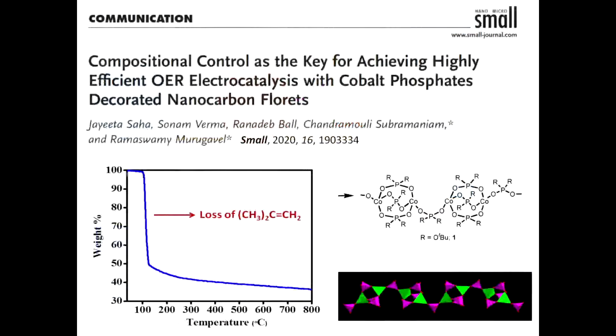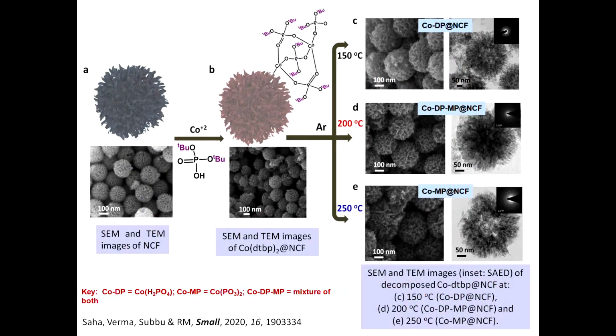If you had followed this TGA, at this point the dihydrogen phosphate is converting into metaphosphate. So what you have at 200 centigrade is a mixture of both dihydrogen phosphate and metaphosphate. And now you hit 250, by the time you have completely exhausted all the POH groups, and what you have is only the metaphosphate. So essentially, dihydrogen phosphate is one extreme, metaphosphate the other extreme, and something in between.